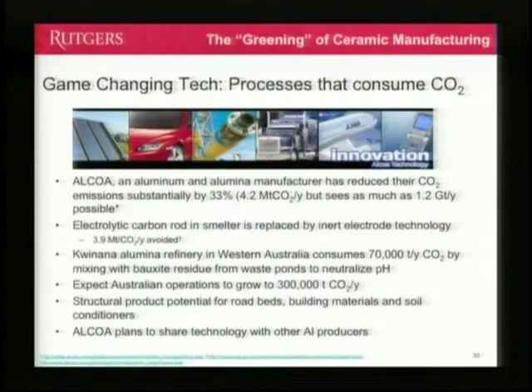Alcoa, in the process of making aluminum, generates lots of CO2 by consumption of their carbon electrodes and all the electricity that's used. So they have this material called red mud, which is a product of the process. It's basically mostly iron oxide and some sodium hydroxide. And so people are using that as an additive to cementitious materials. And because it's highly basic, it also pulls CO2 in.